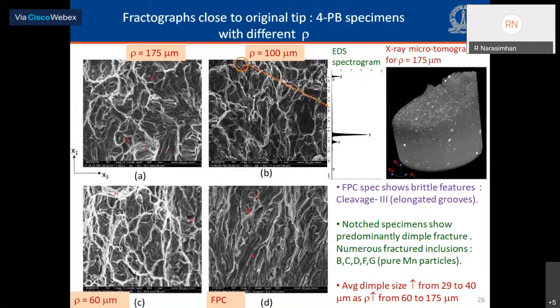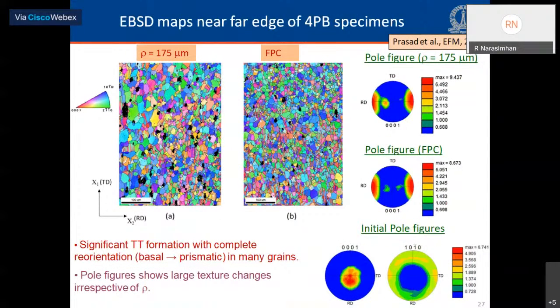And one of the observations which we could make, again through very painstaking metallographic characterization, is that the average dimple size increases from about 29 to 40 microns as the notch root radius increases from 60 to 175 microns. These are EBSD maps from the 4-point bend specimens taken at the far edge of the specimen for 2 specimens, and you can see profuse tensile twinning with most of the grains having completely reoriented, and the pole figure shows a basal to prismatic change in the texture, a very vast texture change as compared to the initial pole figure, which is shown at the bottom.